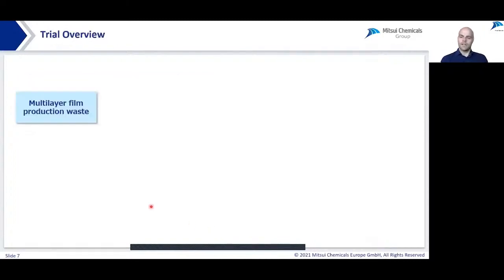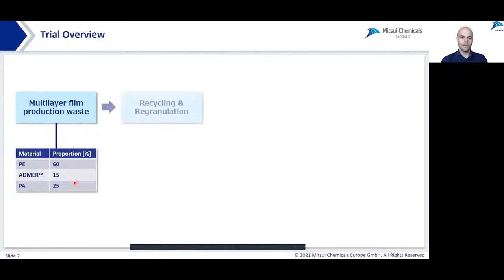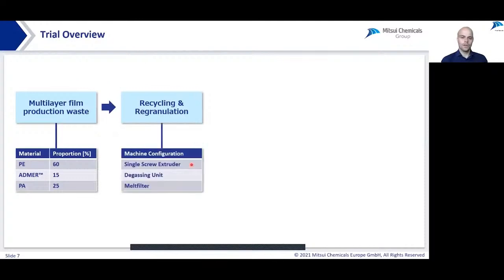We performed some trials and took a multi-layer film composed of 60% PE, 15% ADMER tie layer, and 25% PA. We chopped it and processed it in a special recycling machine consisting of a single screw extruder with degassing unit and melt filter, produced a new monolayer film from the recycling material, and analyzed the resulting film